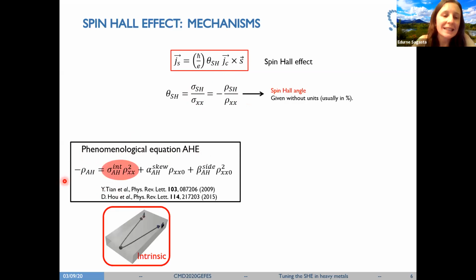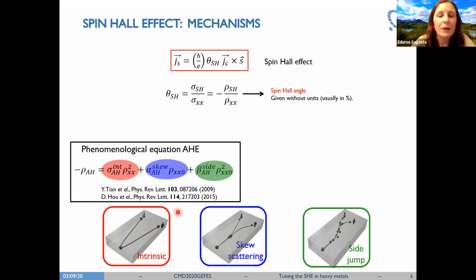So here we can see that the first contribution corresponds to the intrinsic contribution. The intrinsic contribution relies on the spin orbit coupling that is inherent to the electronic bands of the spin orbit metal. And then we have two extrinsic mechanisms, the skew scattering and the side jump, where the spin orbit coupling comes from the impurities that we have in the host material.